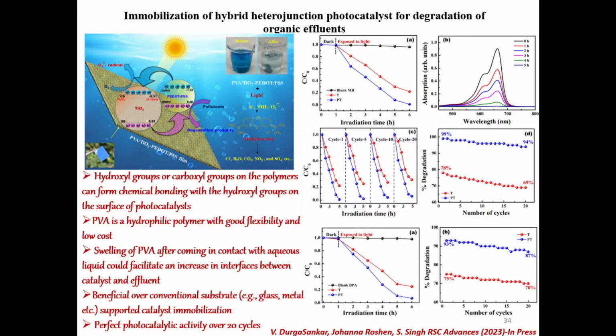So it's obviously beneficial over the conventional substrates, and you can have a perfect photocatalytic activity for over 20 cycles. If you look at the stability here, this is 99 to 94% for about 20 cycles of these films.